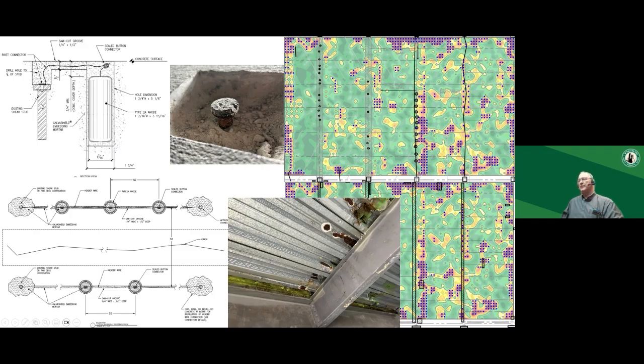This is how we protected those shear studs. You drilled a hole in the top of them. We put a rivet in the top, and we wired them over to the anodes, and that was put in all along these.